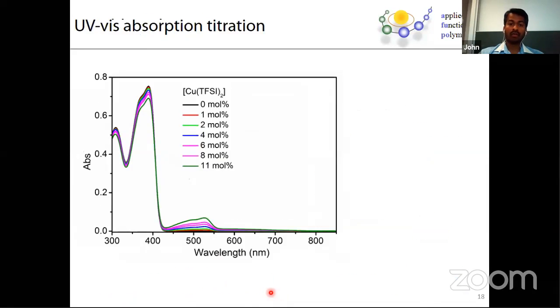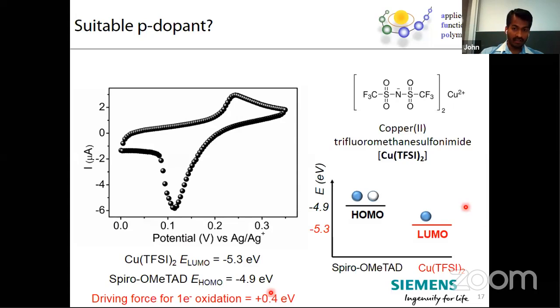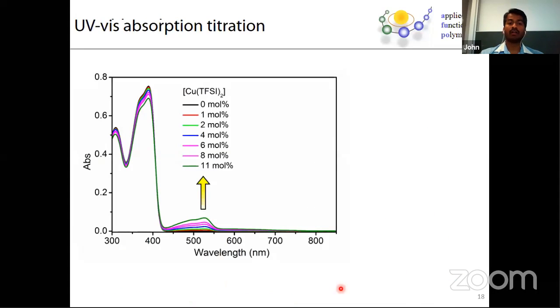And now we started to see whether it is really oxidizing or not. As I said, theoretically we knew that there is a possibility because we have 400 millielectron volt of driving force, but we wanted to see practically whether mixing copper TFSI and spiro produces oxidized species. So we carried out a UV-visible absorption titration experiment. In this experiment, we took a spiro solution in a cuvette, and then we started adding little amounts of copper TFSI to the system.